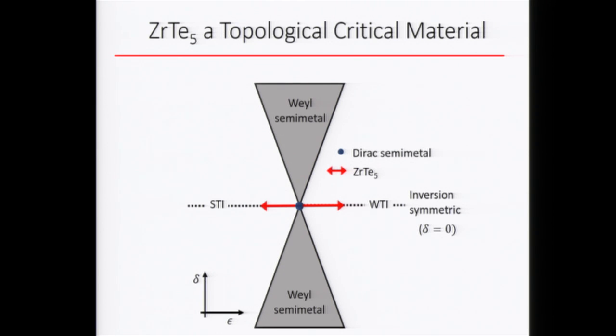So different groups report differently. There are STM measurements saying 80 millielectron volts, and then there are ARPES reports, for example from ZX, reporting something like 18 to 20. And then there are magneto-optics measurements saying this is about 10. And for our measurements, our estimate is between 10 and 20.